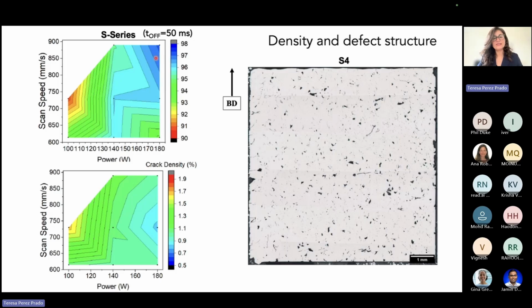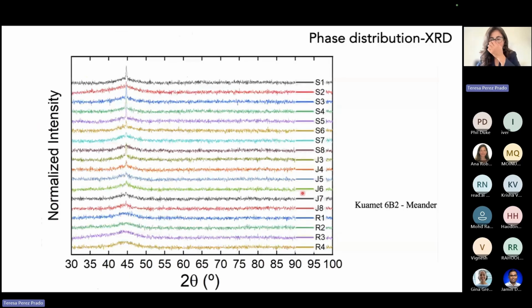This was 98% at some point, from 90 to 98 within this relatively large window. Again, here you have a representative optical micrograph. I think this is the highest density sample. We still have some cracks, so we were not able to fully get rid of the cracks, and the crack density throughout this region is between 1 and 2%. Crack area fraction, measured from the optical micrograph, and this is 2D, so we know there are limitations to this kind of measurement, but at least the density was looking better. What about the amorphous fraction?